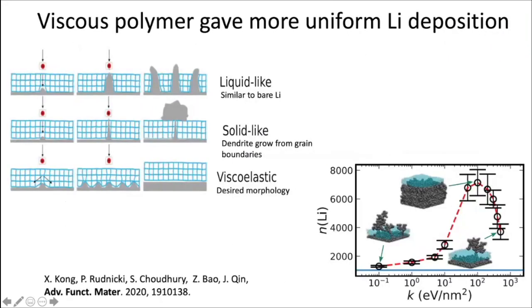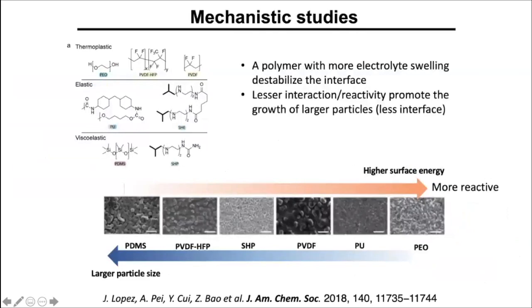nanostructures. And at the same time, our colleague Jian Qing has been using modeling to investigate the role of mechanical property of the polymer coating. And his modeling also suggests that a viscoelastic polymer coating on the surface of the lithium metal tends to give growth of a more dense and uniform layer of lithium metal, giving the desired morphology. So this information also coupled with our systematic study of surface energy and the polarity and solvation of various different polymer chemistry to investigate their impact on the Coulombic efficiency,